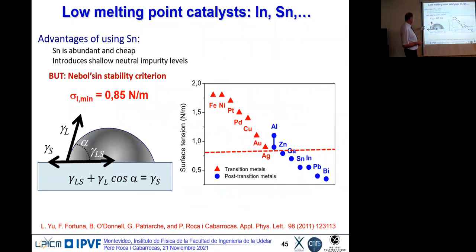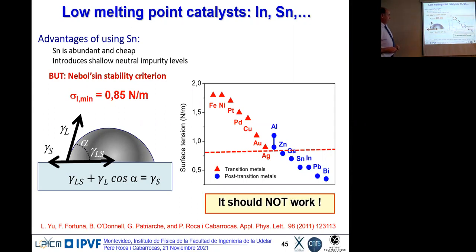And the issue here is that there is a criterion saying that if your metal has a surface tension which is below 0.8 value, then the drop's surface tension is not strong enough, the surface energy will win and you will make a pancake, a pizza. So it should not work. And we love things which don't work in this research. If it doesn't work, then you have something fun to look for, right?